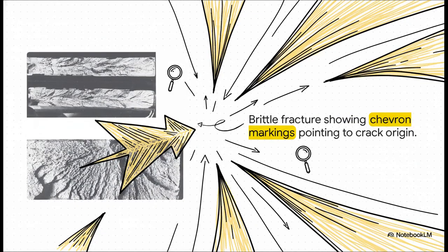And this brilliantly illustrates the stark contrast when we switch over to a brittle fracture. Zooming back out to a macroscopic view, you don't see any of those fibrous dimples or stretched-out metal. Instead, you get these sharp, V-shaped chevron or fan-like markings. These lines are amazing because they act like giant physical arrows left behind at the crime scene. If you follow them, they point directly back to the exact microscopic initiation site where that fatal crack began.